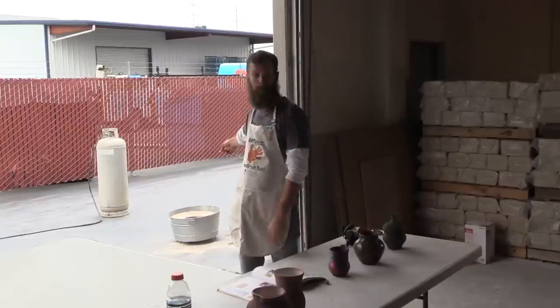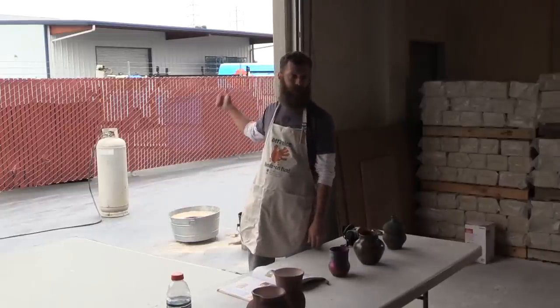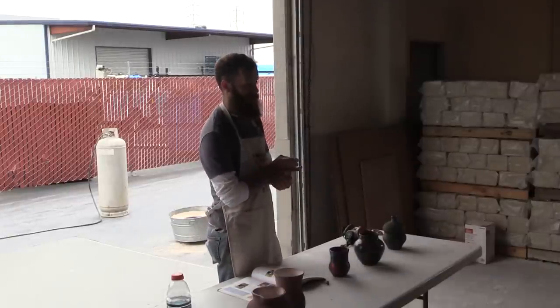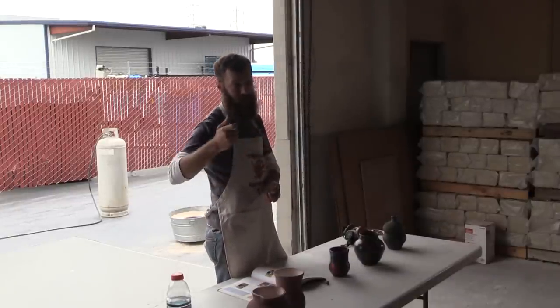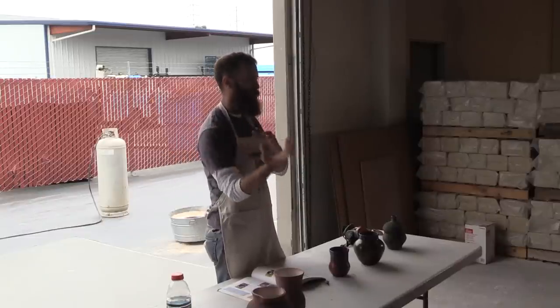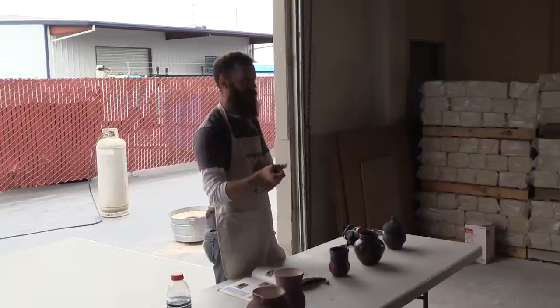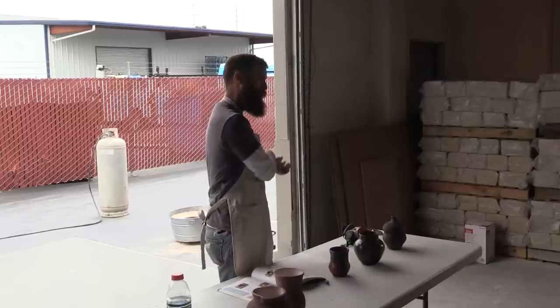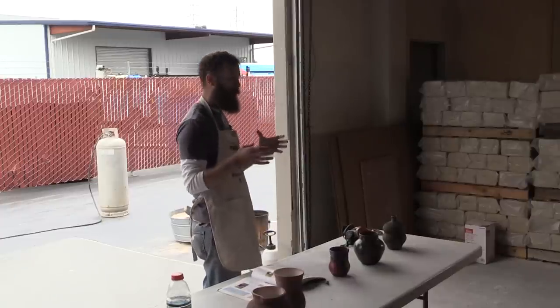When I go to put it in the reduction chamber, I definitely recommend everyone come around and take a peek. When I take it out, it's going to be black. When I spray it with a mixture of the 91% rubbing alcohol, it's going to do these halos of copper and blue and red as the alcohol starts to soak in. When I put it in the reduction chamber, it'll still be kind of black, but as soon as I seal it,